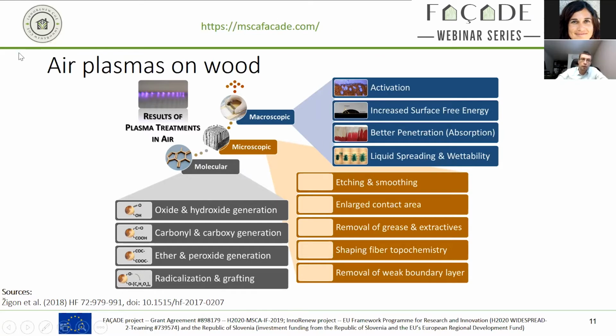So in this case, we're looking particularly on wood, but the same holds true for all sorts of other bio-based materials. And particularly the molecular effects are the very same also on all sorts of polymeric, metallic, and ceramic materials. So one thing that you of course see macroscopically is that there's an activation of the surface, that you change the components of the surface free energy. In air particularly, what you'll typically get is a hydrophilization, a better spreading of water. What you're also typically getting is a better penetration of different liquids, in most cases both polar and non-polar liquids. But also liquid spreading, generally wettability. So all these kind of macroscopic effects, and then the further resulting adhesion strength if I'm combining this with a coating or with any kind of glue. These are typical things that are looked at.